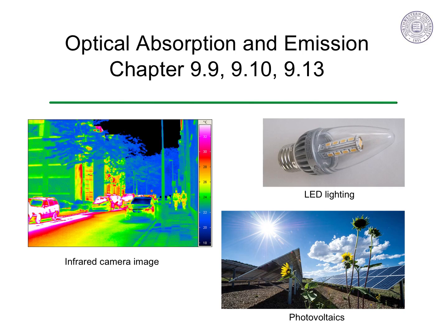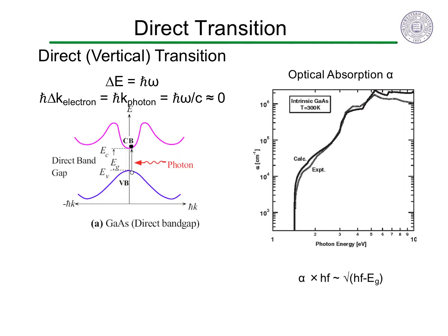Materials for optical absorption can be engineered for detecting light of a particular wavelength or efficiently absorbing sunlight, while materials for optical emission can be engineered for efficient lighting. A photon of light is absorbed or emitted when a single electron moves from one state to another. We talked about how the energy of the transition gives the photon its energy, so delta E equals h bar omega. The photon also gets its momentum from the electron transition, but it is so small the transition looks nearly vertical in an E versus K diagram.